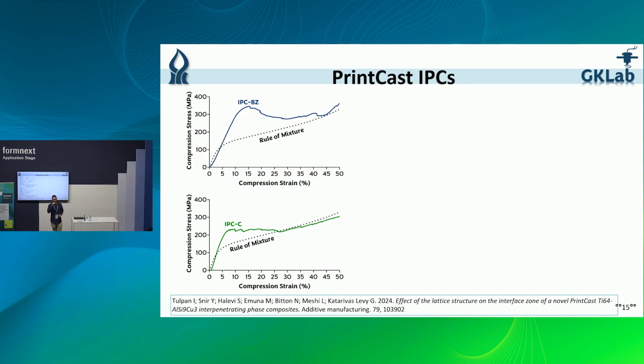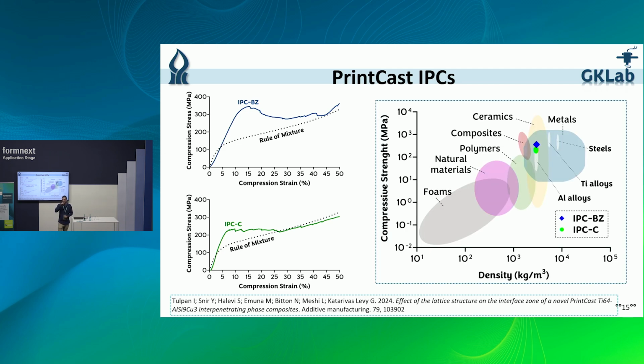We analyzed the mechanical properties of our IPCs, and here we can see the result of compression strain stress testing of both of the IPCs that we produced. We can see a comparison to a rule of mixture prediction, which is a prediction based on the ratio between the titanium and the aluminum for the mechanical properties. We can see that both of our IPCs overperform the predicted mechanical properties. We can see here also a comparison between a variety of different material families in the engineering world. And we can see that the IPCs that we produce have a very high strength-to-weight ratio. We can even see that they have a similar strength to titanium alloys, even though they are, for the most part, made out of aluminum.